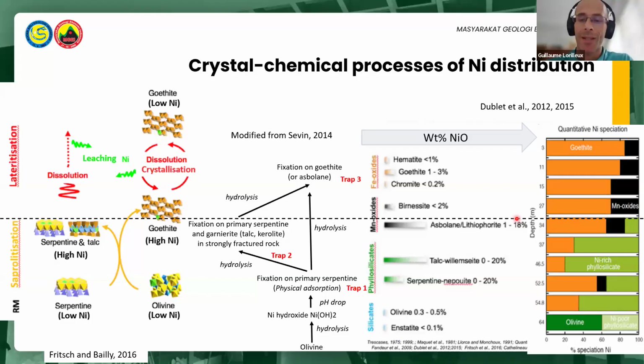The decrease in bulk nickel content in limonite towards the surface might be explained by aging of goethite in situ through successive dissolution and precipitation cycles, as shown here, during weathering in the fluctuation zone of the water table, and also by dissolution of manganese oxides. Adsorption appears to be transitional since after its release from silicates, the adsorbed nickel further passes to the lattice of the goethite or precipitates with it.